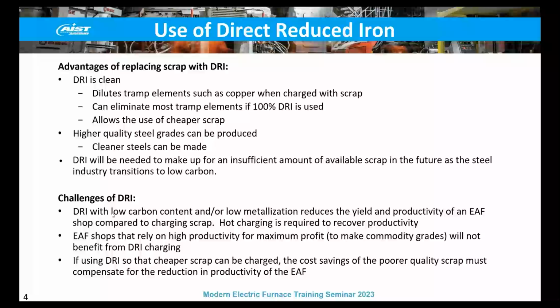Challenges with DRI: depending on how it's produced, it can have a low carbon content and low metallization. Depending on how DRI is handled, it can become reactive and start to reoxidize before it goes into the electric arc furnace, which presents challenges for the EAF. You have to add more fluxes and some type of carbon unit to do reduction. If you have low metallization, high FeO content, EAF shops with high productivity may suffer downfalls of lower productivity because you're trying to reduce oxides in an oxidizing environment, which is energy intensive and kind of counterintuitive.